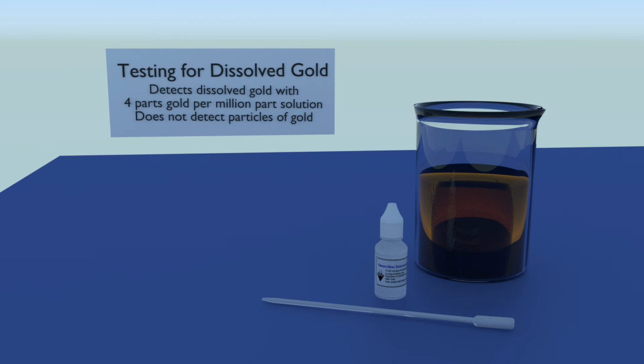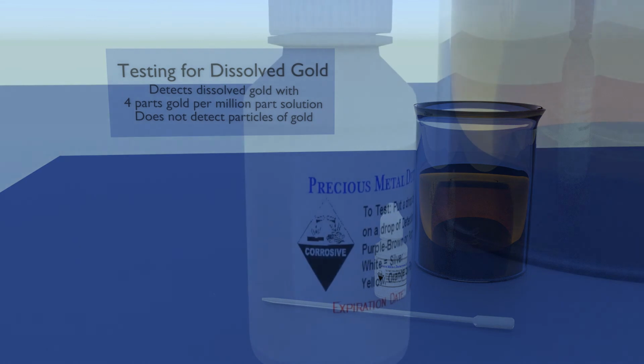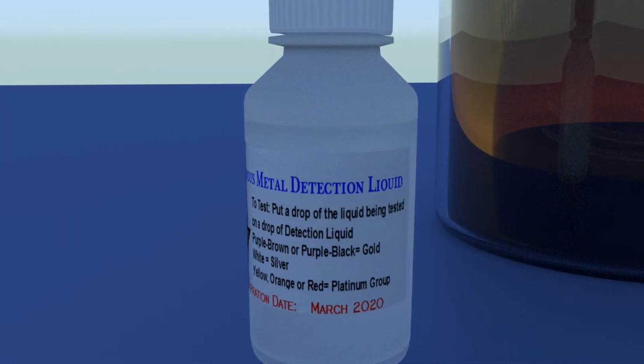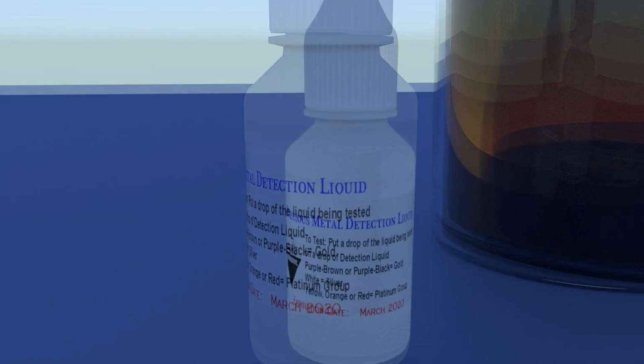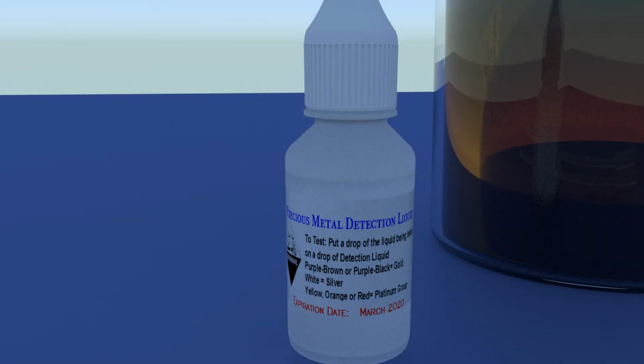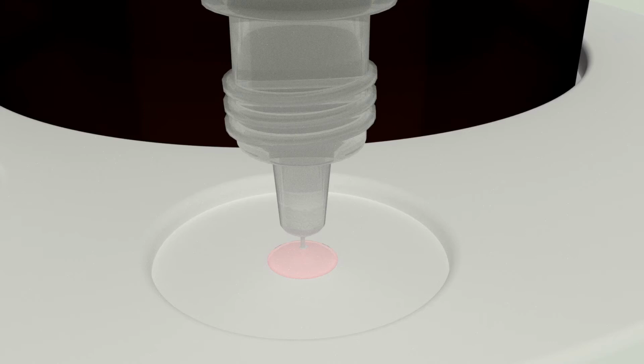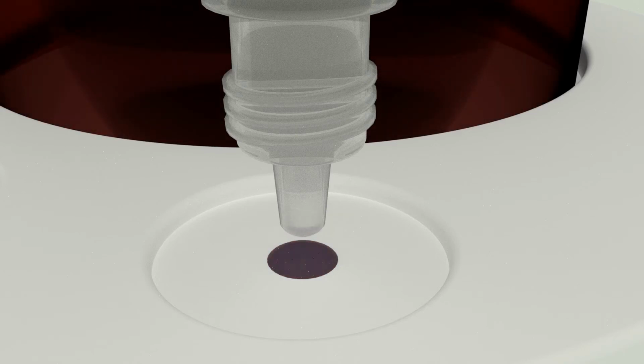If purchasing this ready-made, make sure that the label has an expiration date. And replace the solution when the expiration date has passed. A good ready-made solution will have an effective shelf life of 1 year. Homemade solutions have an effective shelf life of 3 months. This test is simple and very sensitive. It will detect dissolved gold up to 4 parts of gold for every 1 million parts of solution. Particles of gold will not be detected by this test.